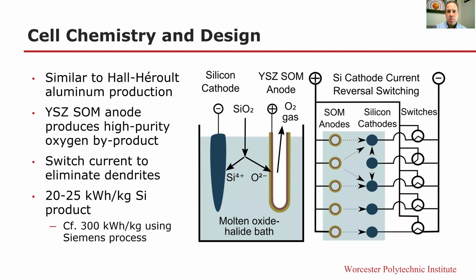So this is similar to the Hall-Héroult cell for aluminum production, which makes tens of millions of tons of aluminum every year at very, very low cost, $1 to $2 per kilogram. So it's a very similar concept, however, with a solid cathode here. The silicon product is solid versus the liquid aluminum that's produced in the Hall-Héroult cell. So the principle is similar, though. You feed silicon dioxide, it dissolves into silicate ions. This Si4+ isn't quite right. It's more like an SiO4 4-.